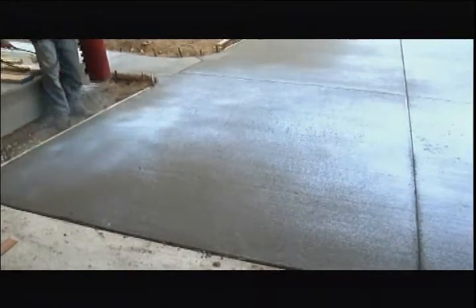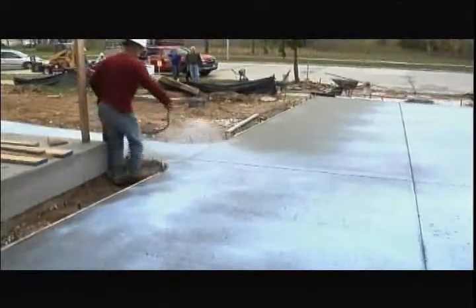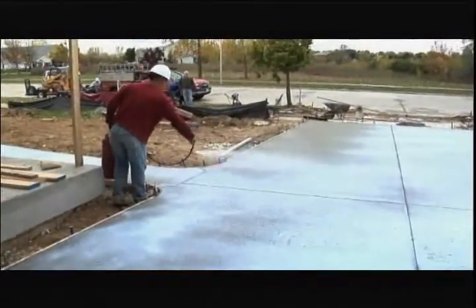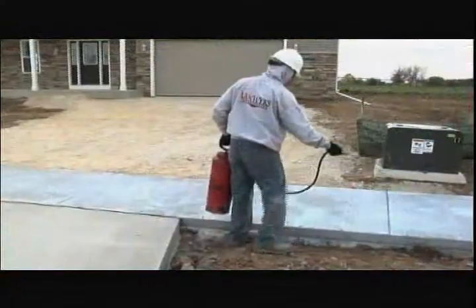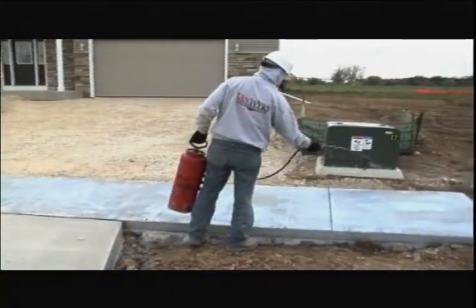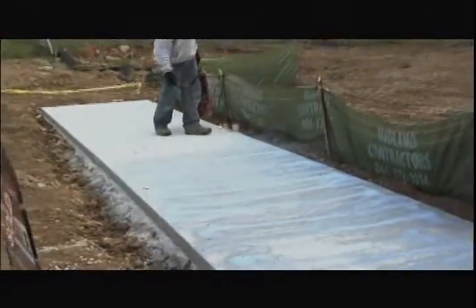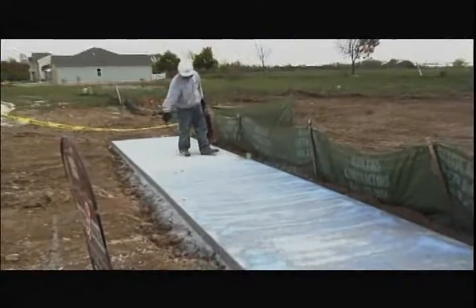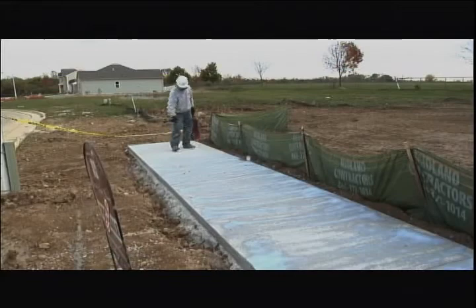The most common is the application of a compound sprayed onto the surface of the concrete immediately after finishing that prevents the concrete from drying prematurely. From about mid-April through mid-September, a sprayed-on curing compound is the preferred method. Regardless of how the concrete is cured, air dry for 30 days and follow with a concrete sealer. Sealing is a process where a protective coating or penetrating water-repellent material is applied to keep moisture and contaminants out of the concrete. Use caution and wise cold weather practices if placing exterior concrete during later months.